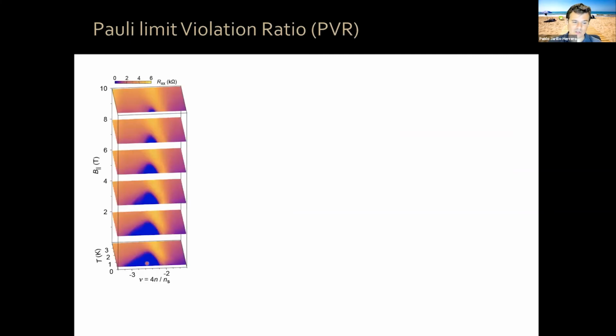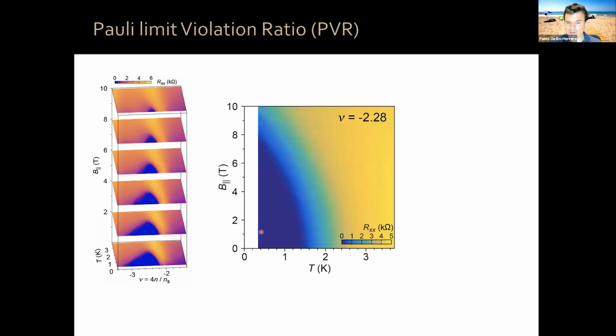In order to determine the extent of the Pauli limit violation, we have to do temperature dependence measurements. So we measure the resistivity versus filling factor and temperature. This is the usual superconducting dome. Now add different parallel magnetic fields. You can see that even at 10 Tesla, we still have a finite superconducting dome. We can now take a particular density and do continuous measurements of temperature versus parallel field. This is the filling factor of minus 2.28.